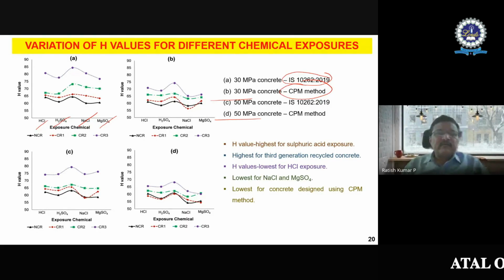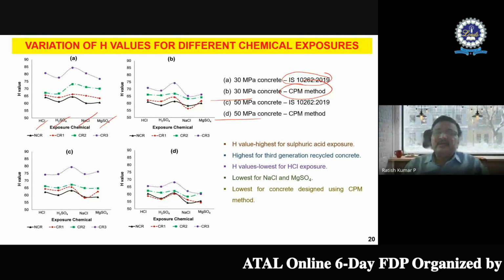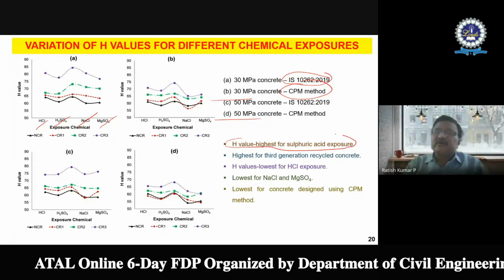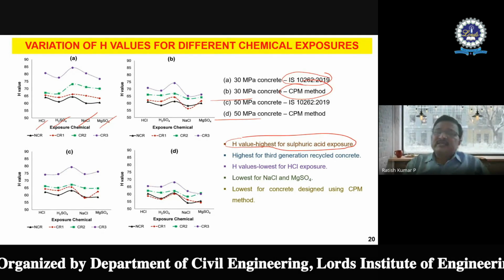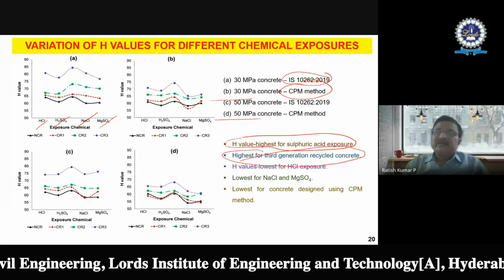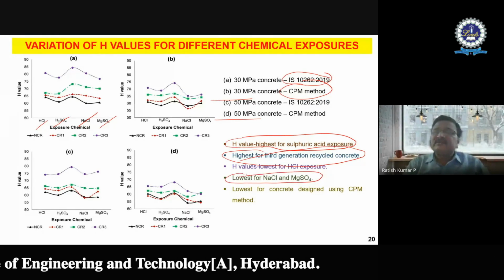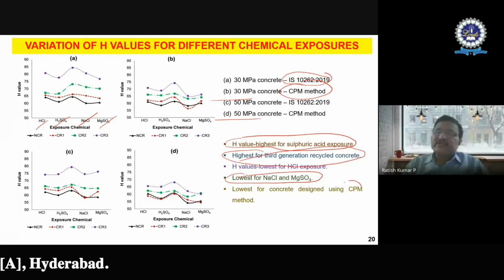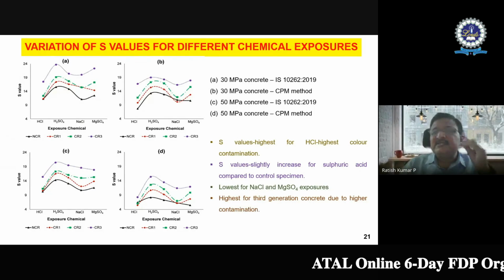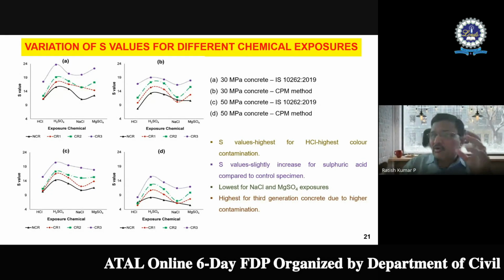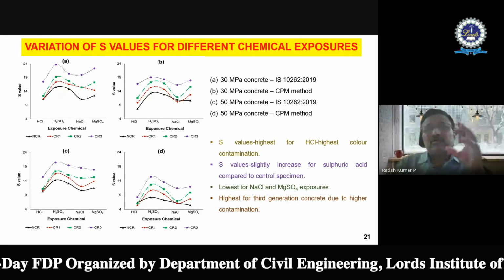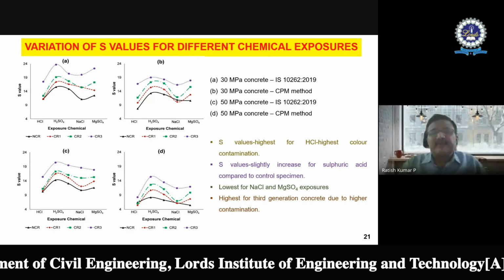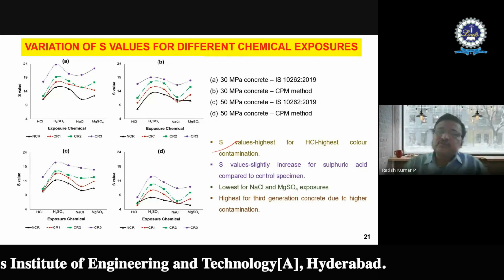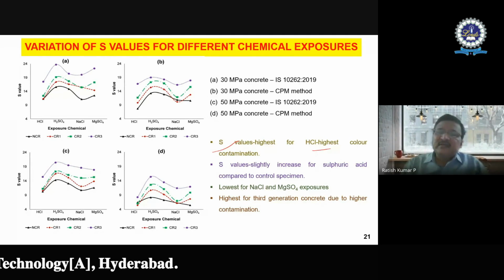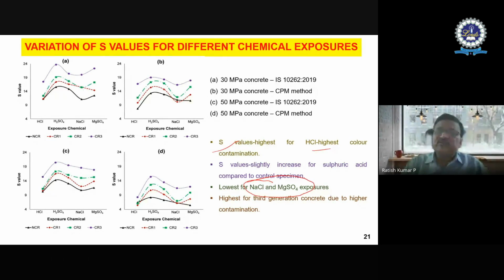And we can see some very good data. You can see the H value is the highest for the sulfuric acid exposure, and it is the highest for the third generation recycled aggregate, and the lowest for NaCl as well as MgSO4. And it's the lowest for concrete designed using the CPM method, which obviously means that the mixes designed using the compressible packing model are more dense, and they could result in a lesser amount of external attack, right? Similarly, if you see the saturation, it is the same: highest in case of HCl, and lowest in case of NaCl as well as MgSO4, right?